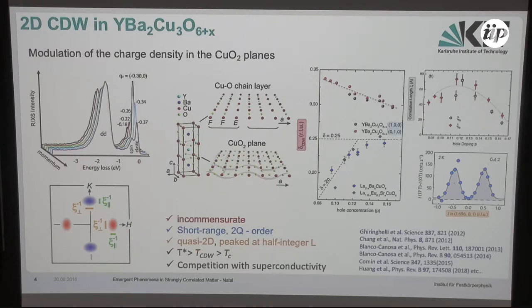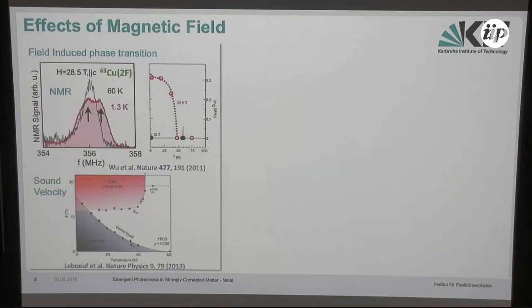It's a short-range order, as I already mentioned, so 60 to 80 angstrom correlation lengths, where its amplitude and correlation lengths are maximized. And if you look along the C-axis, you see this broad structure here, whose half-width spans almost the entire Brillouin zone, telling you that it's mostly uncorrelated along the C-axis. So it's really a 2D order. It appears below the T-star temperature but above the superconducting temperature, and competes with superconductivity. I don't show that here. I will show it later.